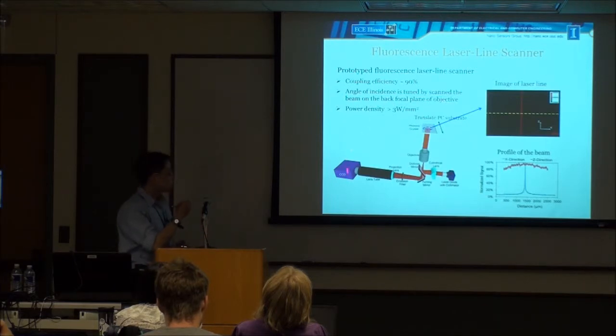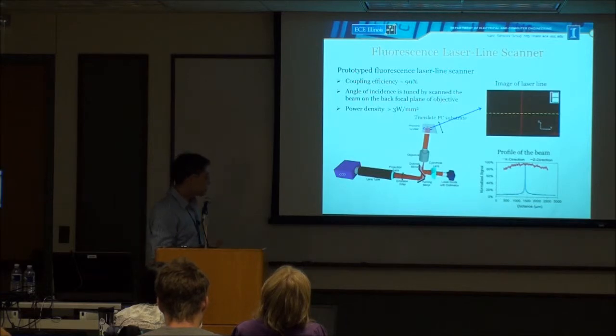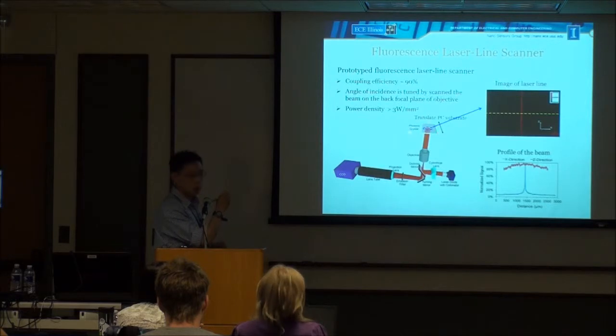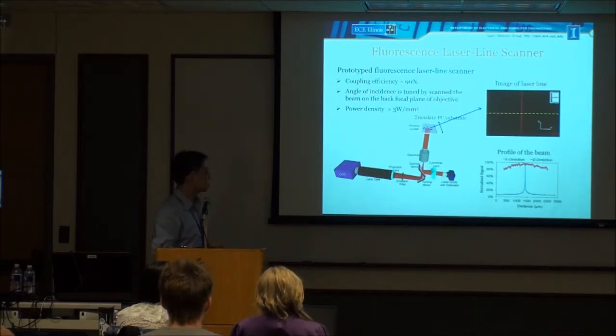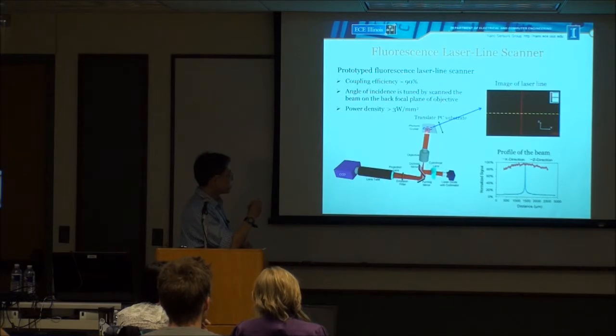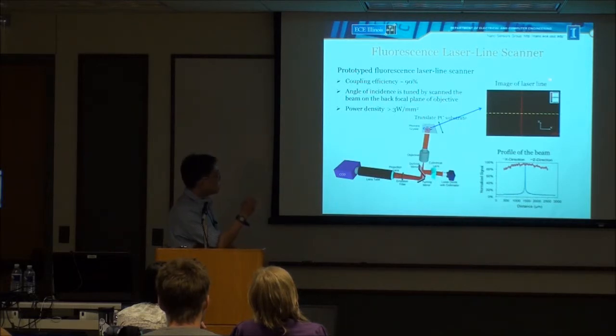So this picture shows the equipment we prototyped in the lab. Light from a laser diode is focused by a cylindrical lens to form a line at the back focal plane of the objective. The objective does a Fourier transform, which flips the line but still keeps the shape of a line, onto the surface of the photonic crystal. So it's possible to tune the angle of incidence by moving the position of this line on the back focal plane of the objective.